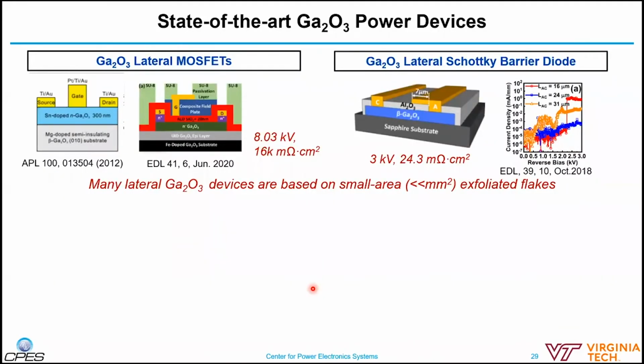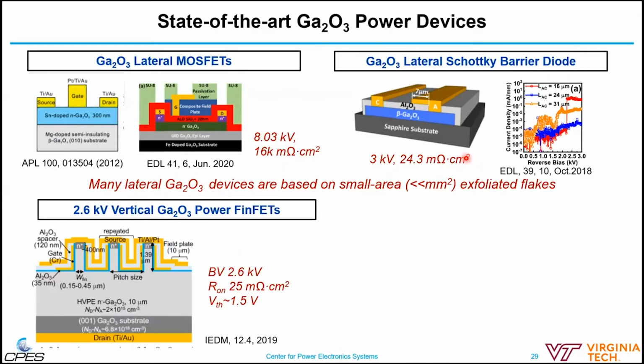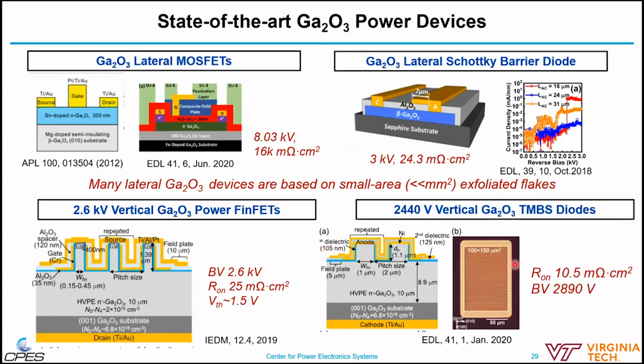Okay, so the gallium oxide devices, and here is just a state of the art of some of the power devices. They can be made as lateral devices, for example, up to 8.03 kilovolts. Of course, the specific on-resistance is super large. There are some lateral gallium oxide Schottky barrier diodes, and they can also be made in a vertical way. For example, this is a vertical power Fin-MOSFET that Cornell demonstrated, very similar to our GaN devices, and also the gallium oxide vertical diodes.